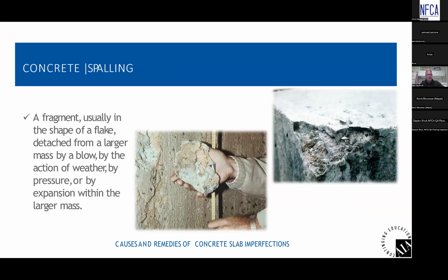Another term you'll see in the industry is spalling, and this is a fracture in horizontal and vertical concrete delivered by a massive blow. So you look at the top right corner, that's a corner of a stair in some capacity. Some sort of direct blow caused that concrete to fracture, and that's called a spall. That's the true definition of a spall. And for that application, it'd be some sort of structural repair material once that's cleaned up and reformed, structural repair product to repair that stair nosing. The vertical wall there, same situation, some sort of massive blow caused a fracture, and some sort of structural repair product to fix that vertical application.